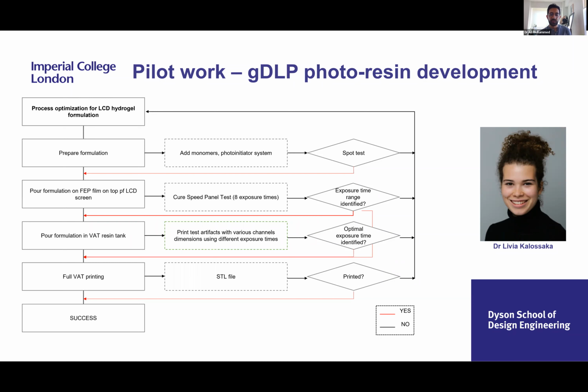In her process, she looks at optimizing photoinitiator combinations and concentrations, the number of bottom layers that you need to attach to the build platform, exposure time for the bottom layers, and exposure time for consecutive layers. It's quite a complex system that you have to work out with trial and error.